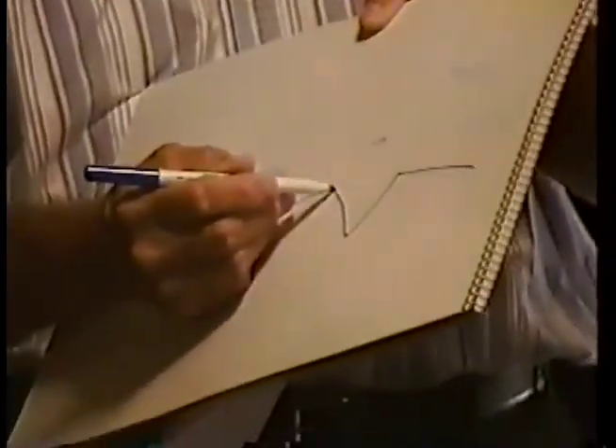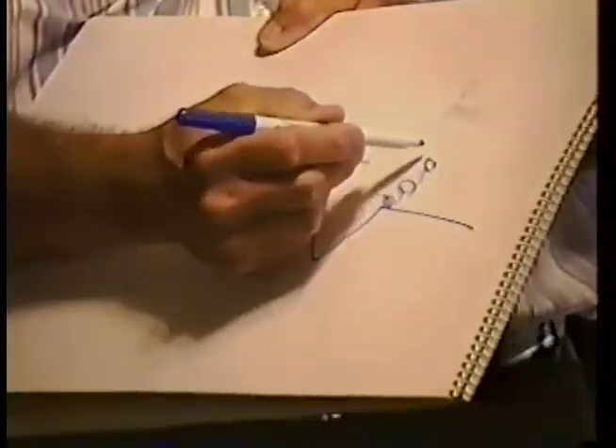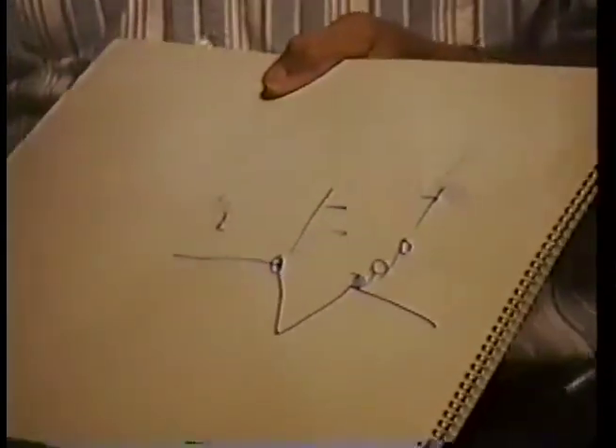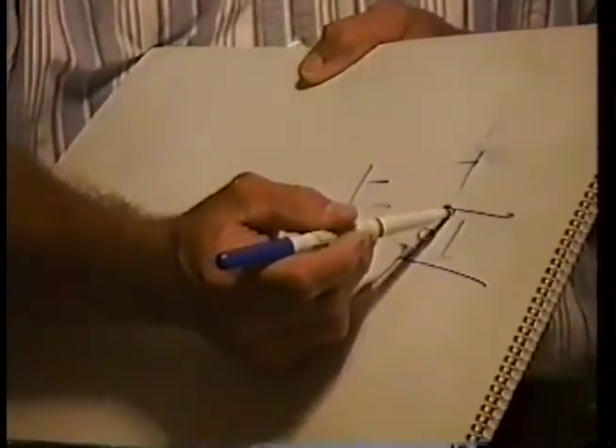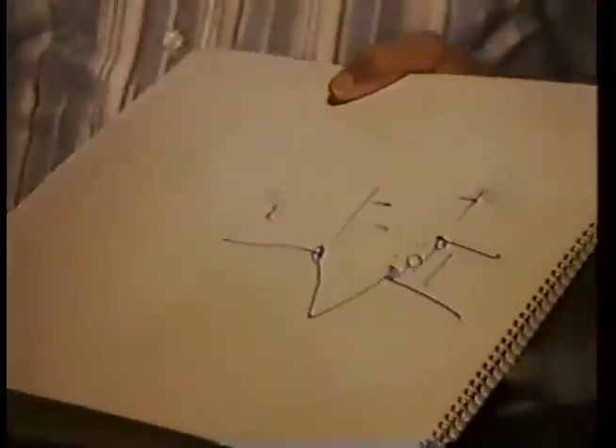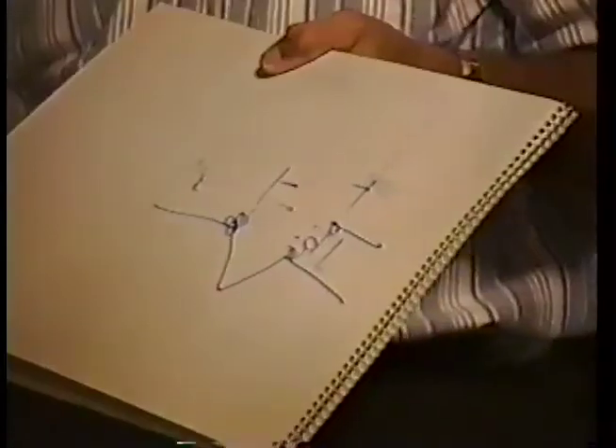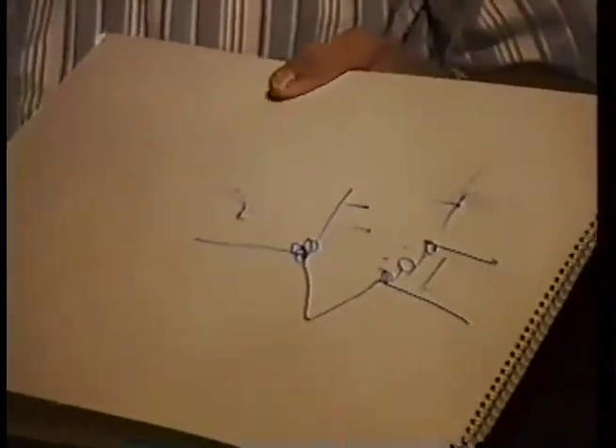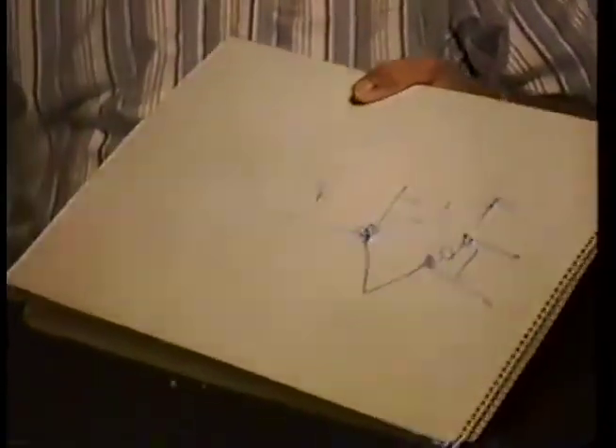With chrome, you have a crater caused by a pit. First of all, you may have a sharp edge, which we talked about before. It will actually plate away from that, making that hole twice as big as it was. So depending upon the thickness of the chrome that you have, it can control the size of the pit that you have. Now, this is such a common occurrence because you can't control the quality of cast iron that well. The OEMs have a spec that says pits up to 1/4 inch in diameter are permitted outside the ring travel area. That's the maximum that's allowable, and that must be out away from there. Now, if you've got control of your process, you shouldn't be plating 1/4 inch pits to start with.